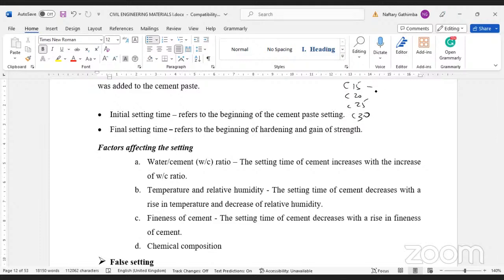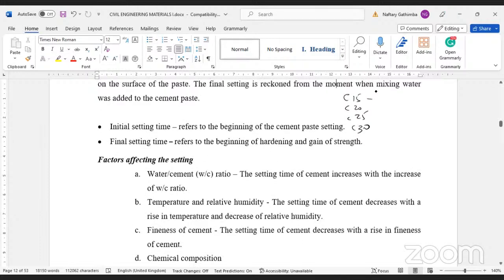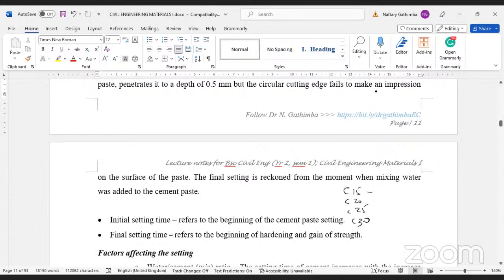And we say now the mixing is the cement; the ratios are cement, fine aggregate, and coarse aggregate. And actually, cement, you'll be hearing the word binder. I keep repeating the word binder because we can have other cementitious materials that are not necessarily hydraulic cement, like geopolymer. For class 15, the ratio is that one part of cement will go with three parts of fine sand and six parts of coarse aggregate. For class 20, we have one part of cement with two parts of fine aggregate and four parts of coarse aggregate. For class 25, you're saying is one part of cement.